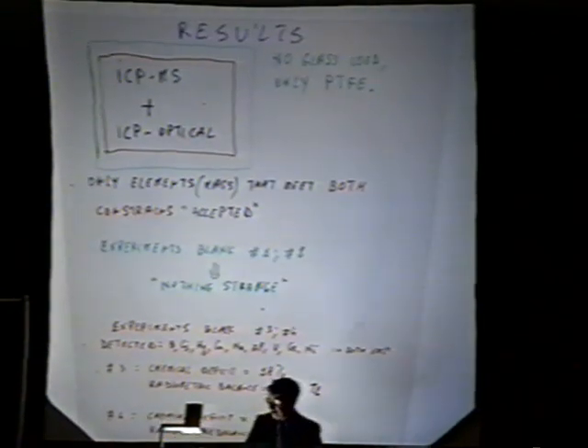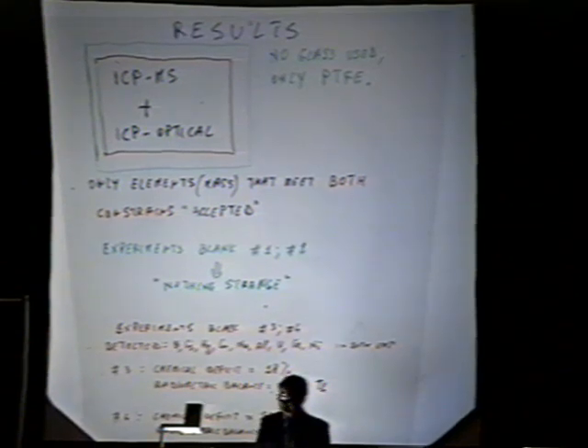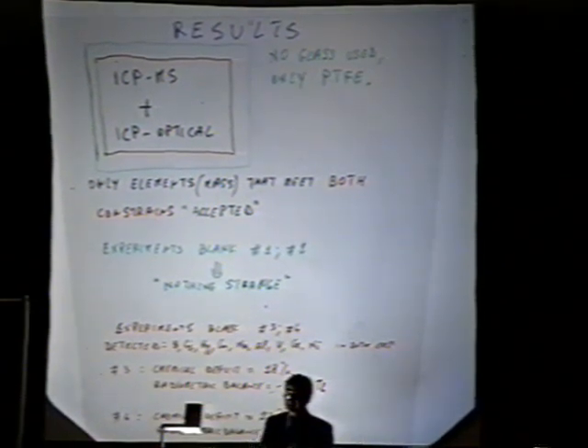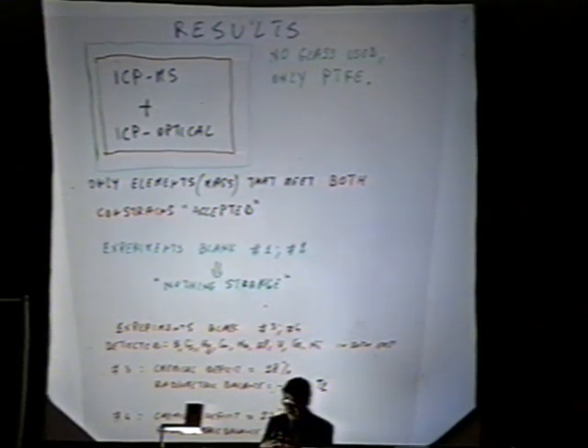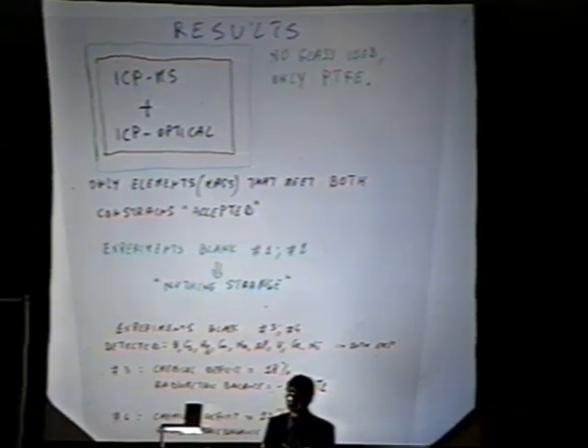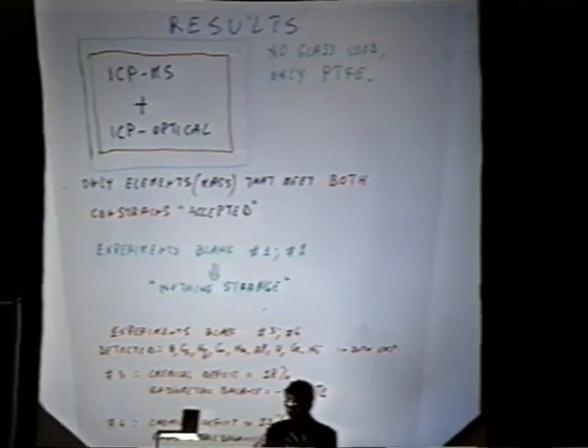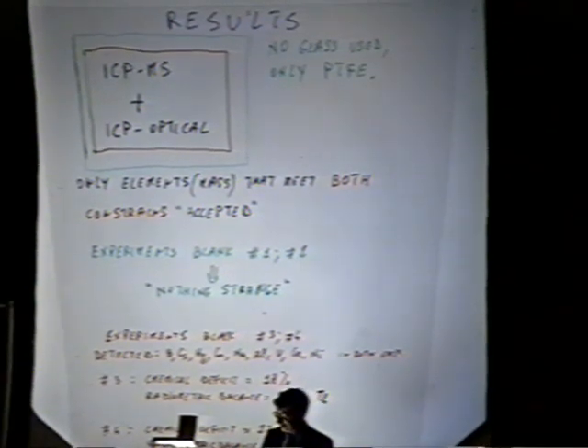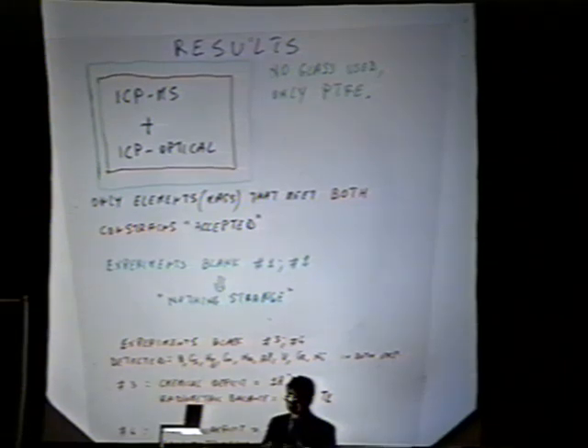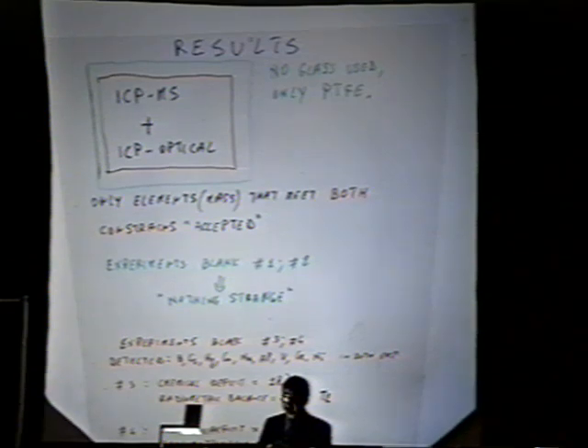The results are the following. Using only ICP mass spectroscopy, we detect a lot of mass. But when you match it with ICP optical, about 90% of what you detect disappears. So I think it's mandatory to use both techniques to be sure about results. Anyway, even under this strong constraint, you get something. Moreover, we recommend not using glass to collect the liquid and solid, but only Teflon, because basically we use fluoric acid, so the glass can leak boron, silicon, and other elements.